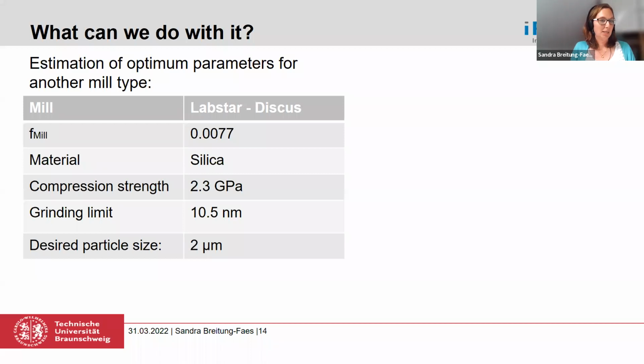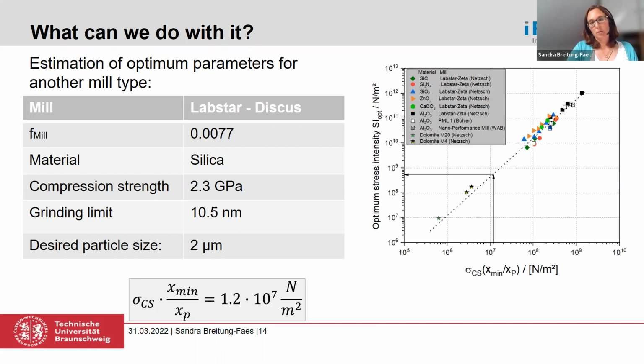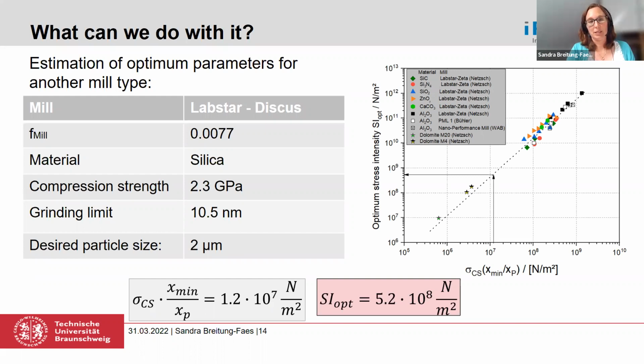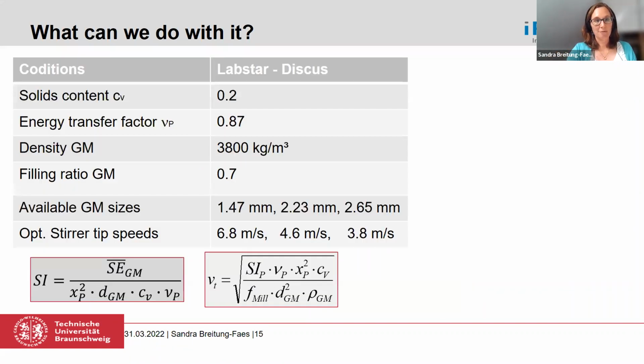And let's say we want to have a particle size of 2 microns. Then we can calculate out of the material parameter, which is like this, and go on with my curve and see where the optimum stress intensity is located. You can do it directly by the graphic. I have a fit function for it and use it, and so I get a very clear value for the stress intensity. And now with this value, you can at least fix your parameters you would like to have, like let's say the solids content you would like to have, the grinding media you have available, the filling ratio, and so on. And in our case, we had 3 different grinding media sizes available, which are shown here.